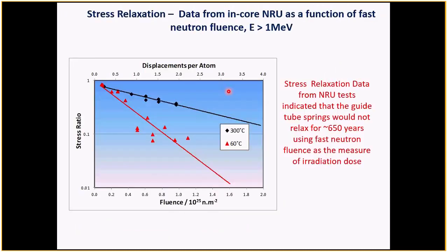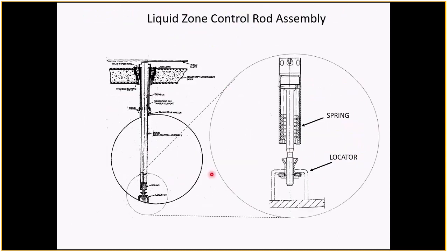Here in the periphery, we have a much higher thermal neutron spectrum compared to the fast neutrons. In the CANDU reactor, the ratio of the thermal neutrons to the fast neutrons right here is about 20,000 to 1.